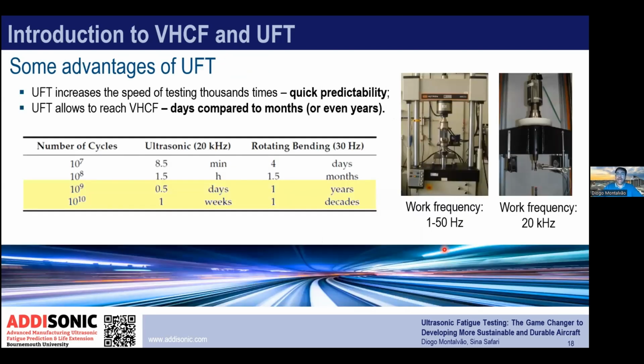But one of the advantages is that if we compare, say, a universal hydraulic test machine from Instron, that typically works between 1 to 50 hertz, and an ultrasonic fatigue testing machine that works at 20 kilohertz, you can see you don't have anything on this end, whereas here you need 2 clamps. And if we do the math, and if we consider 30 hertz, in this case I placed a rotating bending, but could be anything, compared to 20 kilohertz, to reach the very high cycle fatigue regime, it takes us, in theory, half a day on an ultrasonic fatigue testing machine, and 1 year in rotating bending at 30 hertz for a single specimen working 24/7. This is not exactly true for the ultrasonic because of the heating. We need to stop. So it might take us a few days, maybe 3 or 4 days, until we get the crack.